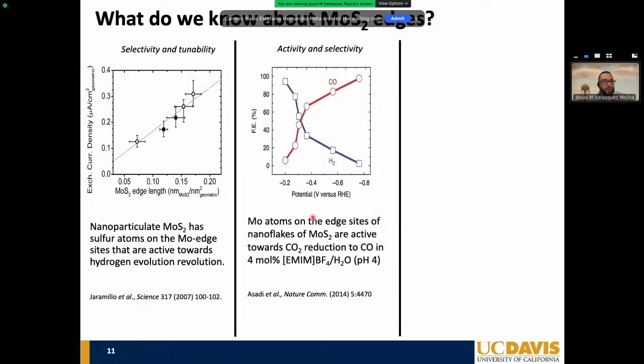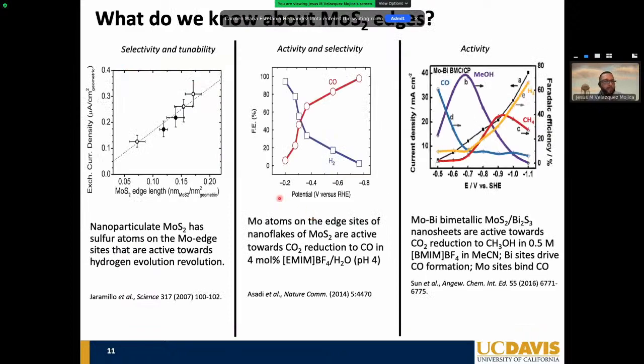So here I'm just showing you some of the representative work out there. Like I mentioned, a lot of work on molybdenum disulfide for hydrogen evolution. This is work done by Jaramillo, where he showed that if you increase the number of edges, you increase the number of active sites and improve the overpotential required to split water to produce hydrogen.